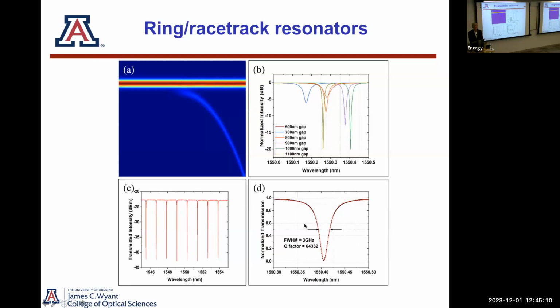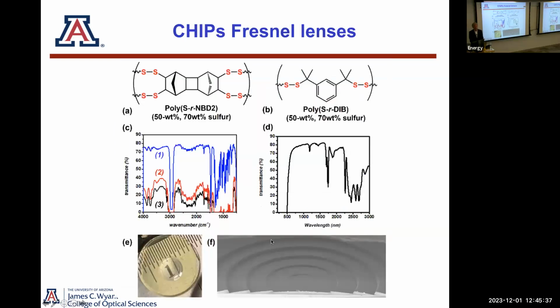And we got a nice Q factor, which is a measure of how good your resonator is. And 64,000 is a good initial number. Silicon, I showed you earlier, has lower Q factors. Silicon nitride, we have silicon nitride resonators, I'll show you in a minute when I'm wrapping up, that have a Q of 2 million. So you can get very, very high Q resonators that are integrated photonic devices now. So this is a good initial number. Okay.